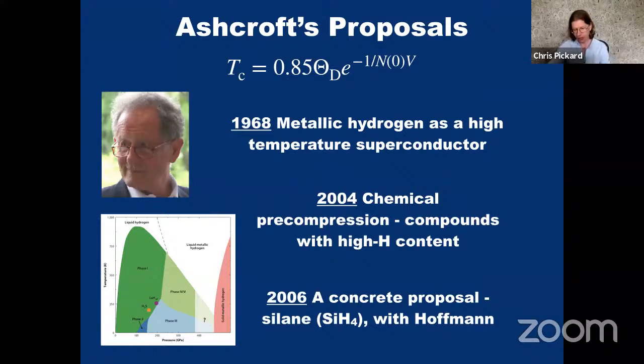He came back with a new suggestion, which was: how about we add something to this hydrogen? You can either think of it as doping the hydrogen or adding some chemical; he described it as pre-compressing the hydrogen. So you add some other element to hydrogen, and that has the effect of the hydrogen appearing to be at a higher pressure. He published a paper on this in 2004. And then he came back in 2006 with a concrete proposal that he worked out with Roald Hoffmann, the theoretical chemist, which was that maybe the element that we needed to mix with hydrogen is silicon.